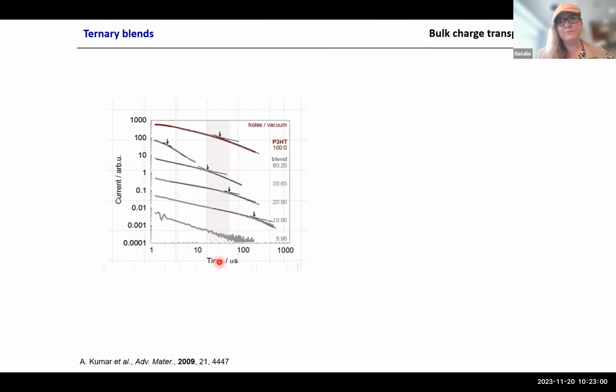And here, a very good method to measure that is time of flight photoconductivity measurement, where you essentially have a film, a thick film, 5 micron. So these are measurements on 5 micron thick films. You shine light on top of your film, you create charges on top, and you measure the time, here the x-axis, till the charges reach the other interface. Polymers are always messy, so how do you see if they arrive? We see it when you start to have a kink in the current. So here, taking the slopes, we can indicate the arrival time.